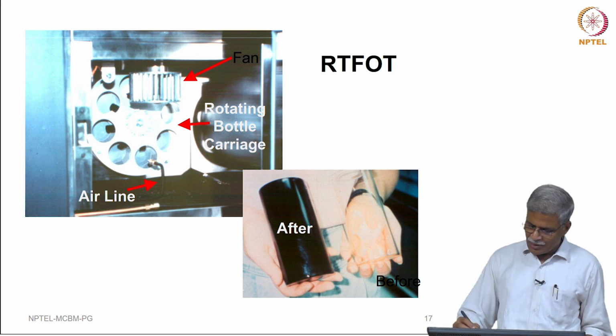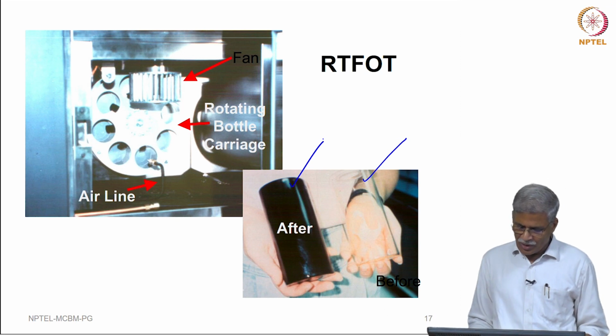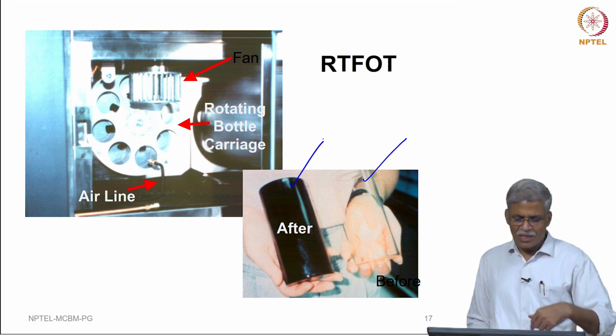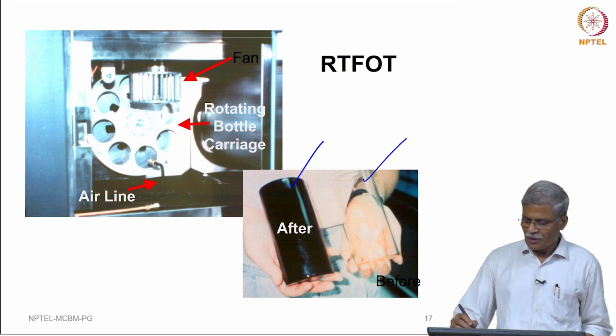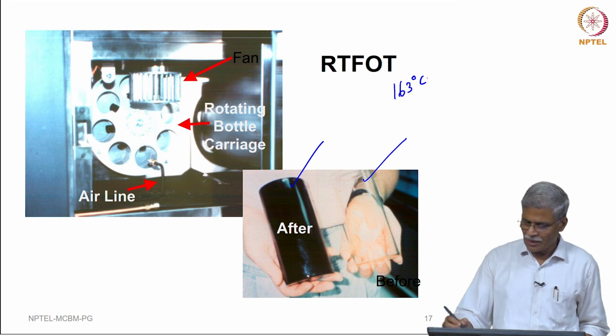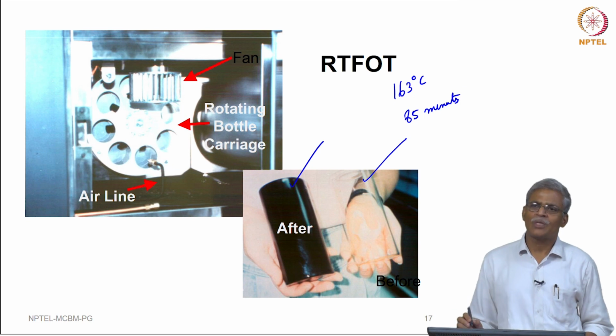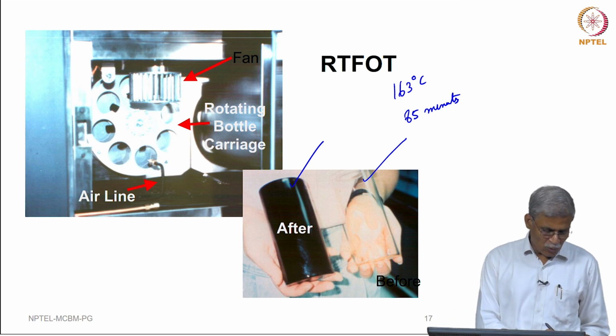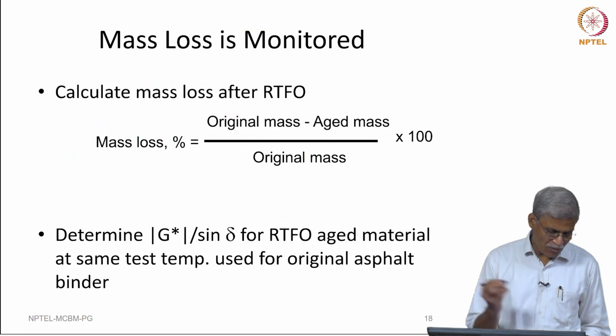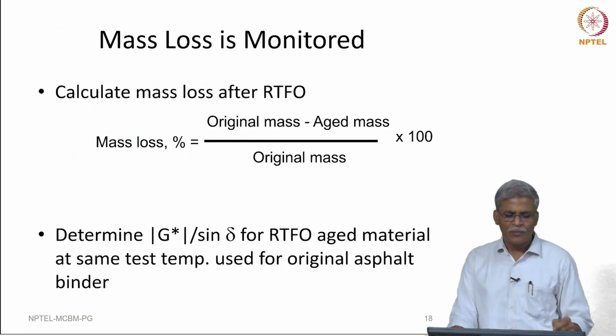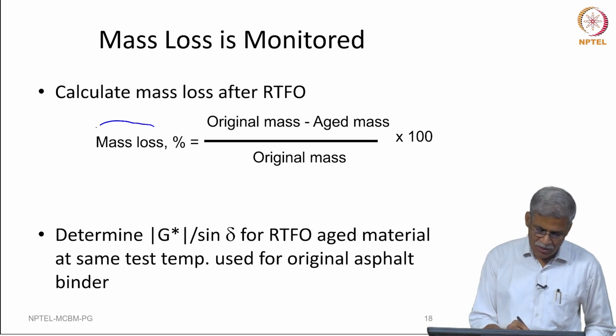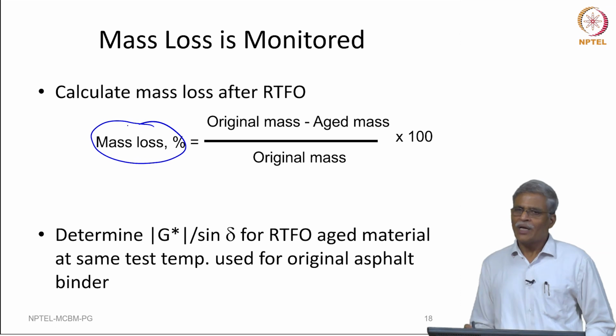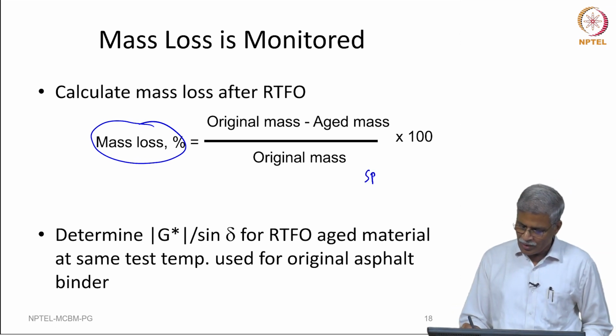So, what you really see here is an empty glass bottle, and we fill it up with around 32 to 35 grams of bitumen, and you have this central carriage that is rotating. The temperature is maintained at 163 degrees centigrade, and we do the aging for 85 minutes. There is an associated ASTM standard for this, you can go through it for the actual specification associated with short-term aging. We also find out the mass loss that happens during this RTFO, and in fact, this mass loss is also a spec parameter, so we need to measure it.